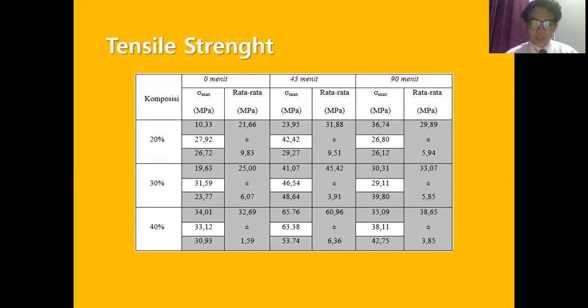Next, there is the tensile strength. At 45 minutes of immersion, the coconut fiber composite experienced the highest tensile strength, compared to 90 minutes and 0 minutes of immersion. This was due to the fact that the longer the fiber was soaked in alkali, the more the fiber core would be damaged, but the lowest tensile strength was obtained at 0 minutes of immersion. The alkalization process also makes the fiber surface rough, making it easier for the fiber and resin to bond. At 0 minutes of immersion, the fiber is not treated, which makes the fiber unable to bond with the resin.